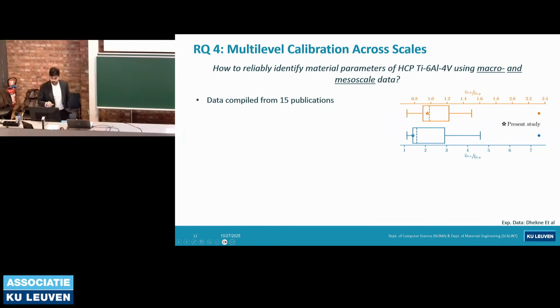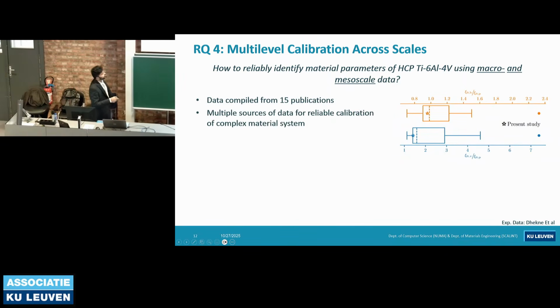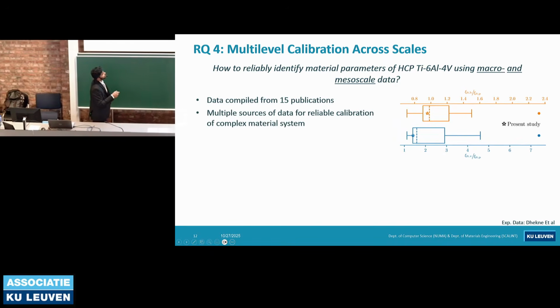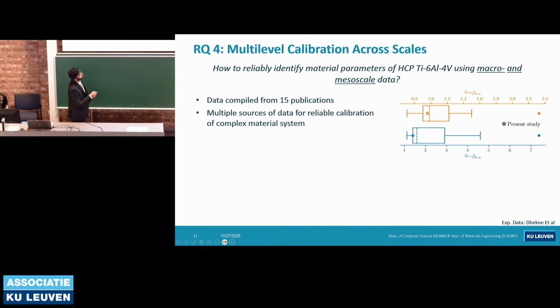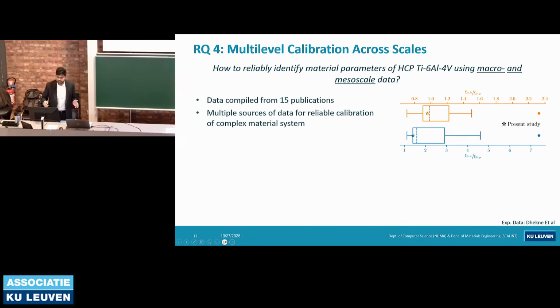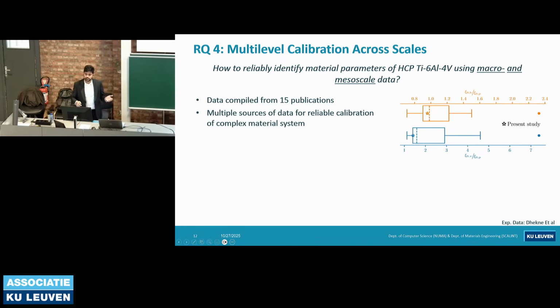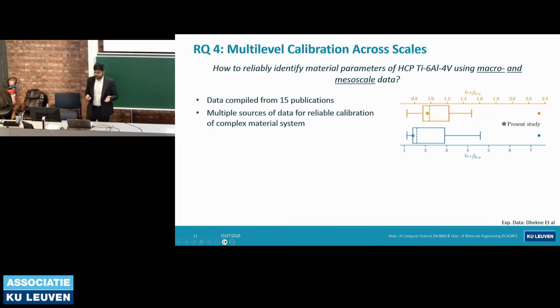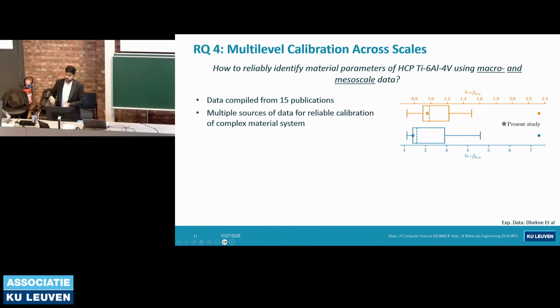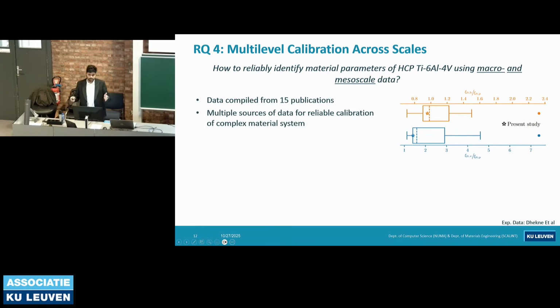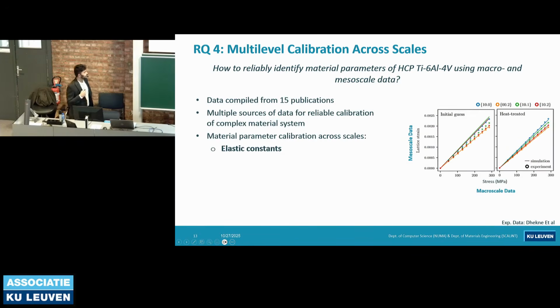Now, this gets even worse when we look at this blue line. Here, 50% of the data reported is between 1.4 and 3. So the range is quite wide. If I'm someone who wants to use such data, and I look it up in the literature, if the range is this wide, then how do I decide which one to use? So the idea is that we need data not just from one scale, but across the scales to calibrate the model. And we perform this material parameter calibration across scales for elastic constants.